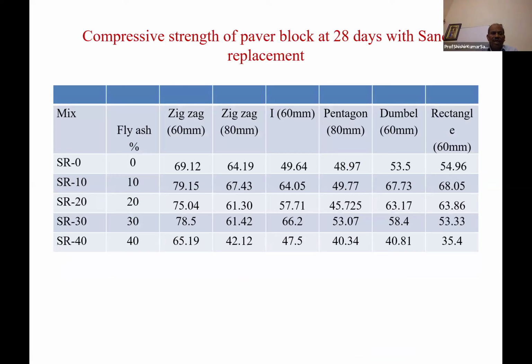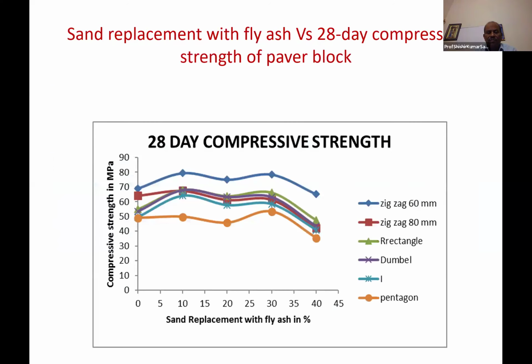So this is the sand replacement with fly ash, 10%, 20%, 30%, 40%. These are the corresponding compressive strengths. As you can see, with an increase of fly ash to 10%, the value increases. Then it decreases. Here it is. It looks like this.